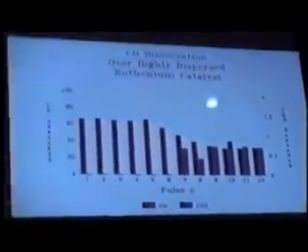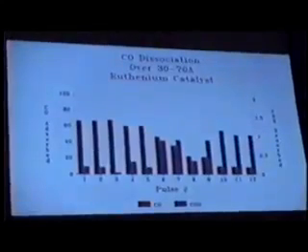During the first 6 pulses with the highly dispersed ruthenium catalyst, we are not seeing any CO2 production. After the 8th pulse, an apparent steady-state CO2 production is achieved. And from the amount of CO2 made and CO adsorbed, for this particular catalyst, under these conditions of 1 atmosphere and 280 degrees centigrade, we calculate a CO dissociation efficiency of about 5%. Now this shows the same experiment with the 30-70 angstrom ruthenium catalyst.